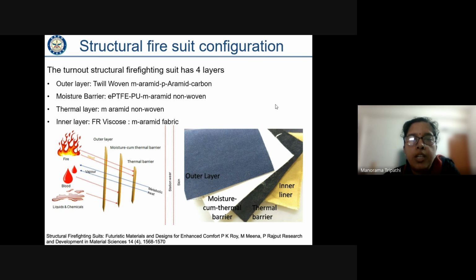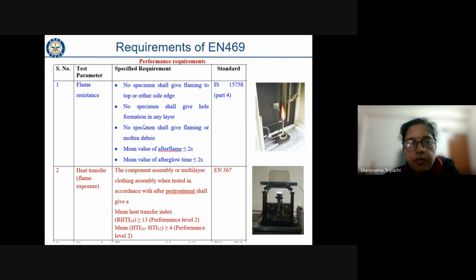So basically, the structural firefighting suit consists of 4 layers. Outer layer is woven meta-aramid, para-aramid, and carbon. Moisture barrier is EPTFE, PU on meta-aramid non-woven. Thermal layer is meta-aramid non-woven, and inner layer is FR viscose and meta-aramid fabric.